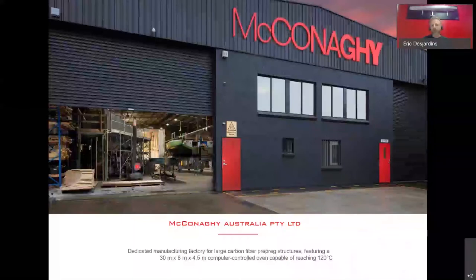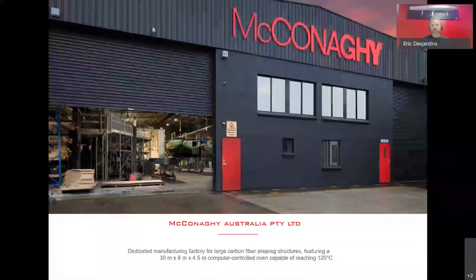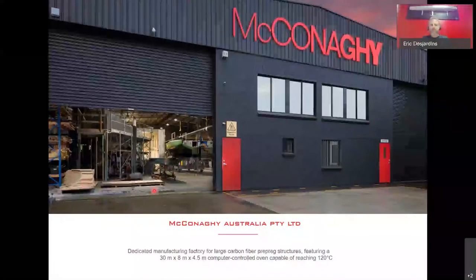And you can see a fin here that's going to go on this boat during the painting process. And here you can see the stack of frames of a female mold for the next project waiting to be installed in the oven. So our bread and butter is really this main oven, which is, as I say, 30 meters long, 8 meters wide and about 4.5 meters high. So it's a decent size oven to make very large structures in one hit.